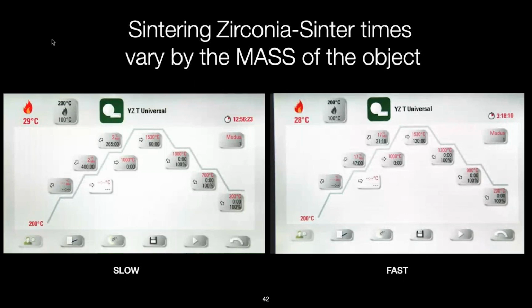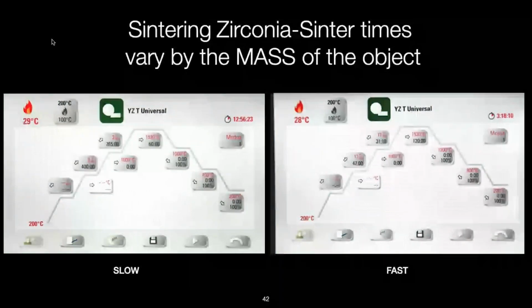And so you're talking 13 hours. The other one is a little bit fast fire where it climbs up and you're going 17 degrees a minute, 17 a minute, and then you drop down. The cooling is really important. So you have fast and slow cooking, but the bigger the mass is, the bigger the pontics are. If you have a tissue flange, whatever it is that you're doing, if they're big, huge cases, you got to get another oven and go home and let it cook and let it cool down and sleep tight. If you try to rush it, it'll fail eventually.